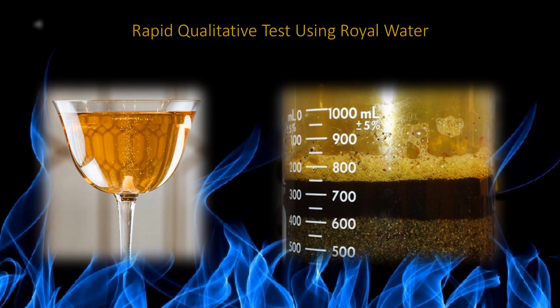Royal water. That is what it was once named. Today it's referred to as aqua regia. This powerful acid solution is 3 parts concentrated hydrochloric acid to 1 part concentrated nitric acid. Place about 1 gram of ore into a beaker, add 20 milliliters of aqua regia, heat it, and let the material dissolve for about 20 minutes or so, then dilute with approximately 150 milliliters of distilled water.